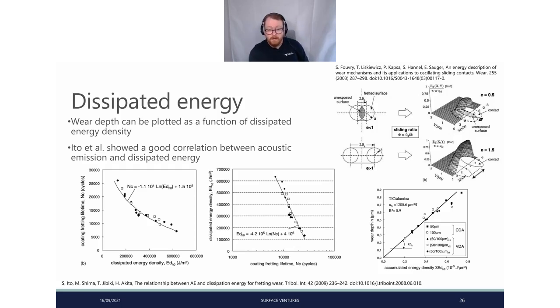If you then increase the sliding ratio, drive it into full-scale sliding, you're then going to have energy distributed across a larger area. But we can think about this then in terms of the amount of dissipated energy density, so the amount of area for your fretting contact, the amount of energy that you have. So if you integrate your dissipated energy all along your fretting loops, and then think about that in terms of your ideal area. What is your dissipated energy density? You can perform multiple tests in order to find what your coating lifetime is. And this produces this wonderful little graph here on the left. We can rearrange this. So in terms of fretting lifetime, number of cycles, and dissipated energy.